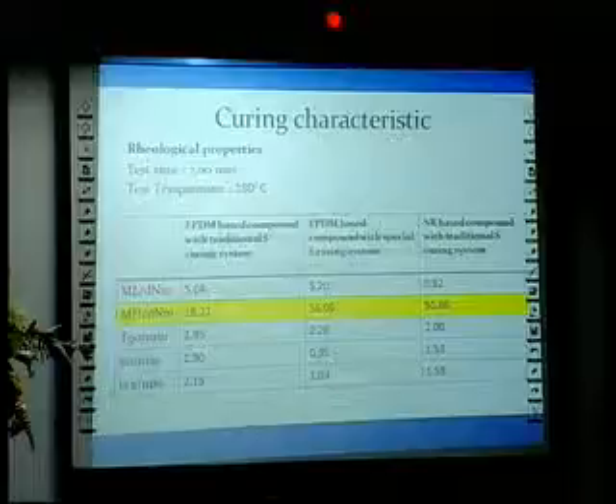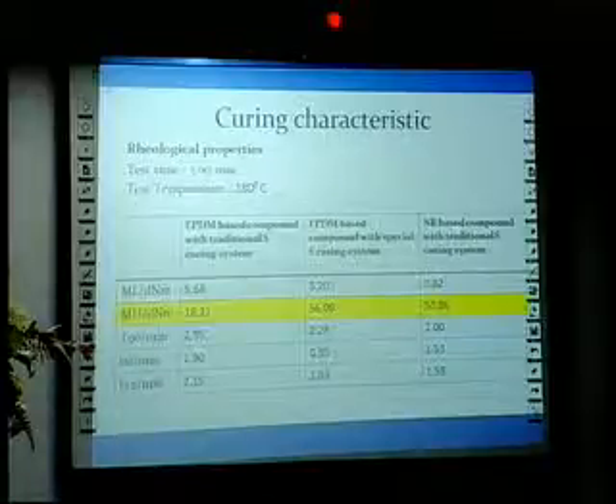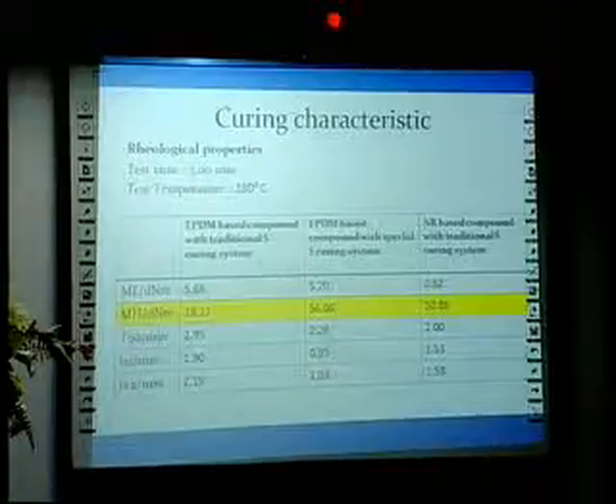Next, the curing characteristics. This table shows the rheological properties. Especially, you can see in the yellow color bar that the high torque value, the MH value, is very low for the EPDM-based compound with the traditional sulfur curing system compared to the others. So it clearly indicates that the EPDM compound specially needs the special sulfur curing.